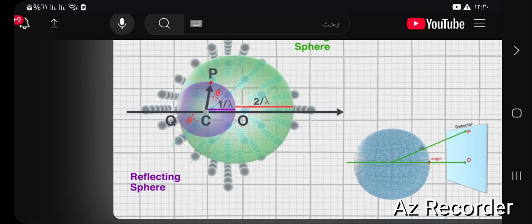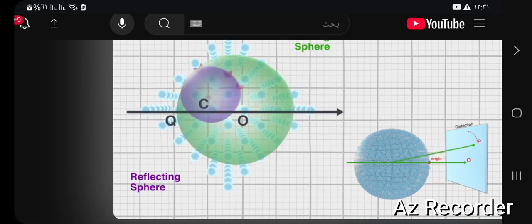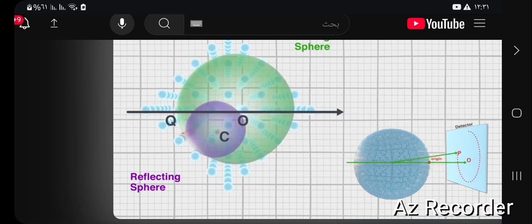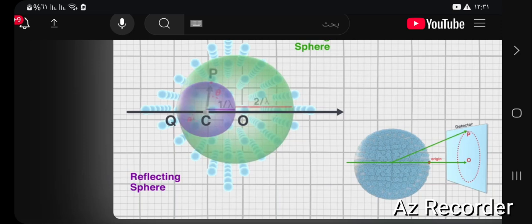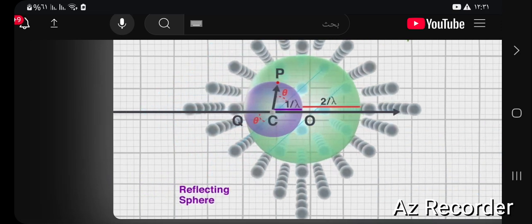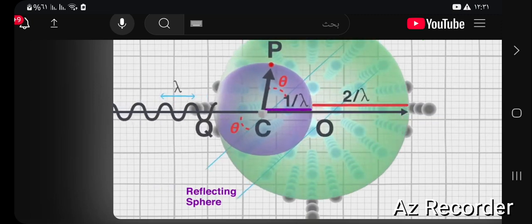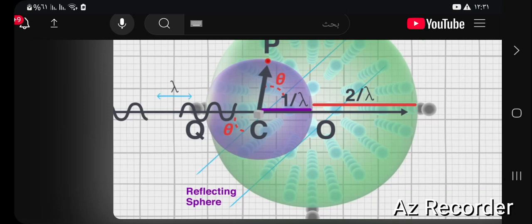With a radius of 2 over lambda, any reflections beyond this sphere are not accessible with this wavelength. Let's try that again. Now watch what happens to the diffraction spots as we rotate the reflecting, or Ewald, sphere within the limiting sphere. Now let's see how we might access more reflections. If we move to a shorter wavelength of X-ray, our spheres will increase in radius due to the reciprocal relationship between the radius of the spheres and the wavelength. This means in going from copper radiation, 1.54 angstroms, to molybdenum radiation, 0.71 angstroms, our sphere will double in size.